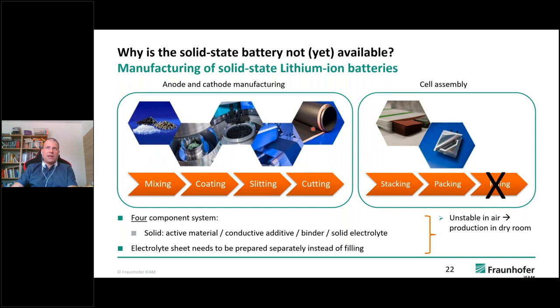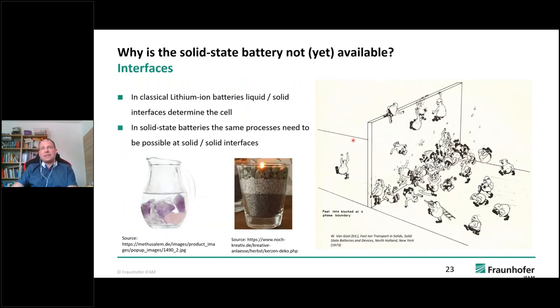But everything is actually unstable in air, because we're using the solid electrolyte, which, if it's not an oxide material, which is probably not made this way, is unstable in air. So this has to be done in a dry room, which increases the cost of production of these cells. And on the other side, we have a big problem with interfaces when we're building the cell. And this is one of the major problems with solid state electrolytes. And you can see in the cartoon that even if we have a very good conductive material, the ions are running very fast inside of the material, when we get to some kind of boundary, which can be between different particles, between active material and the solid electrolyte, or carbon and the solid electrolyte, these determine the overall reaction rate, so to speak, the overall velocity of the ions, because this is a bottleneck.